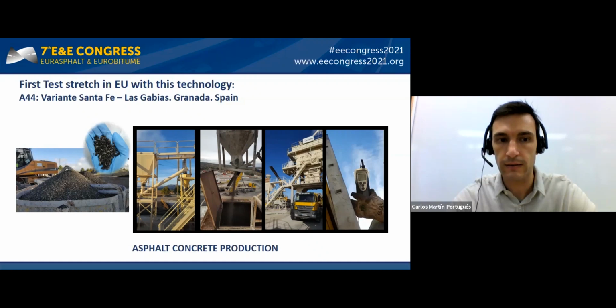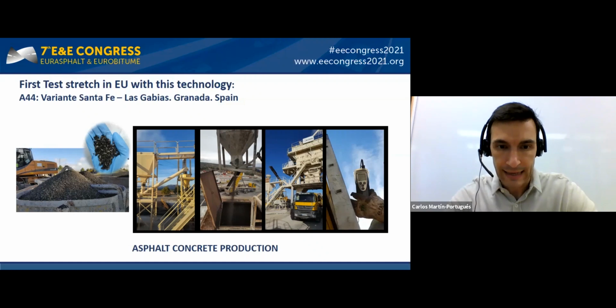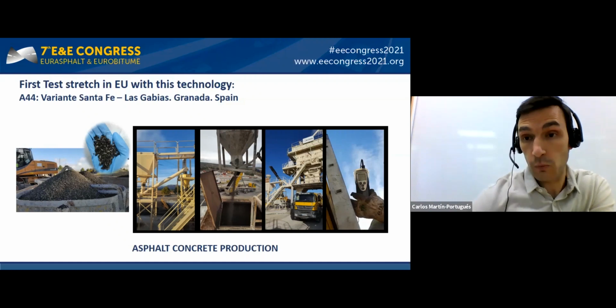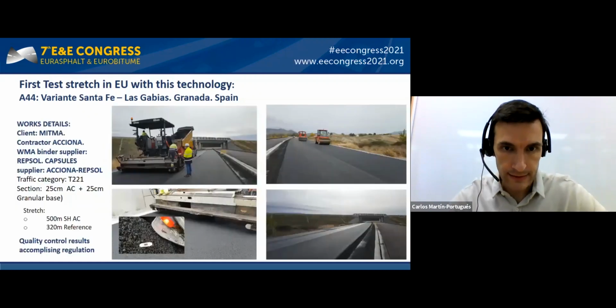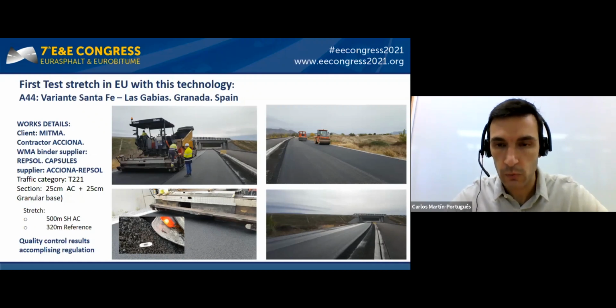For that, we produced the capsules with a similar process to the one we used for the laboratory production, and for the addition of the capsules to the asphalt we used a normal solid dispenser that is typically used for the addition of fibers or lime for the production of modified asphalt concrete, and the result was quite good. And here you can find some details of the job site, and we count on the warm mix asphalt from Repsol, and the result was quite good.